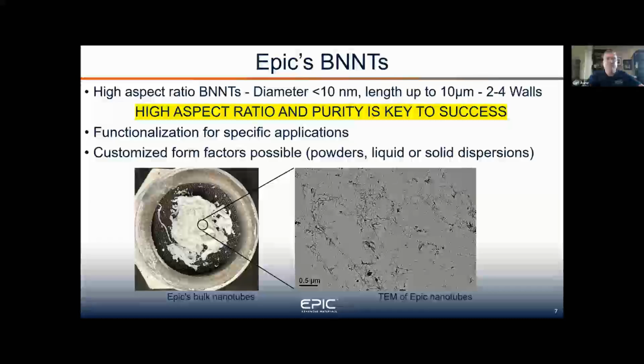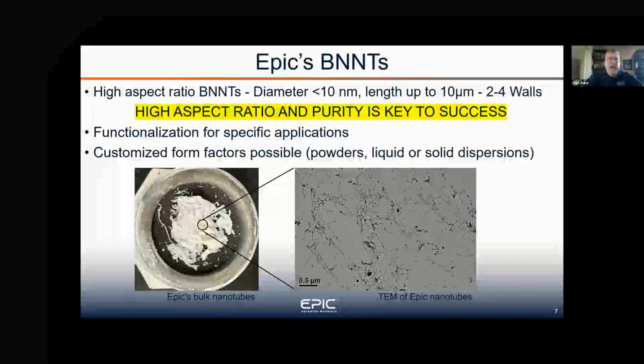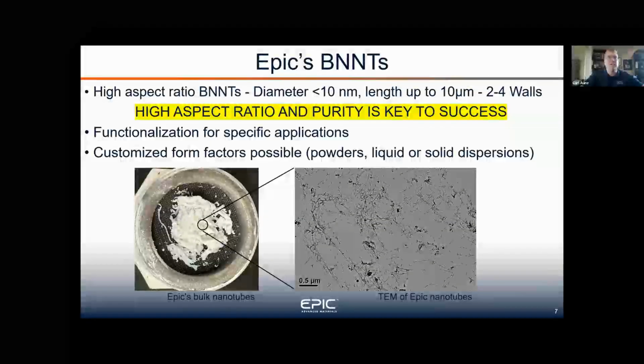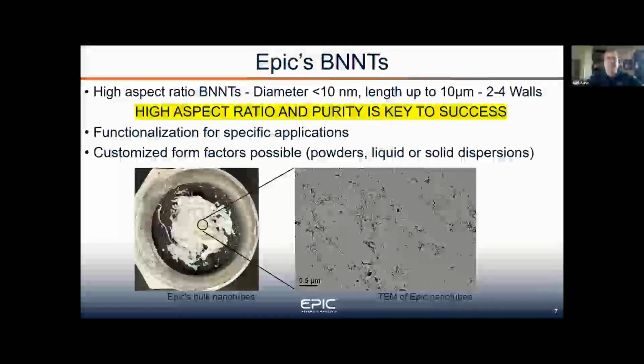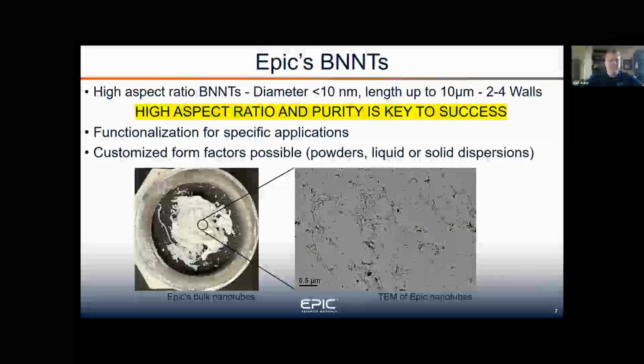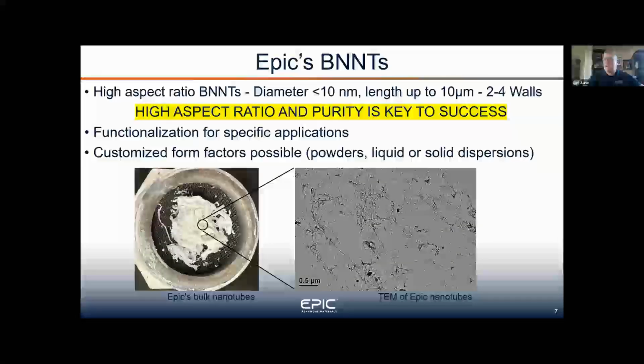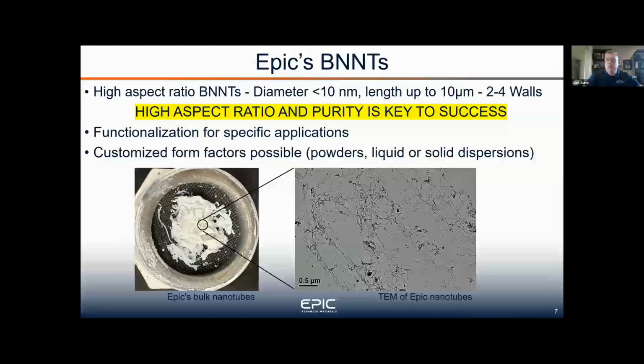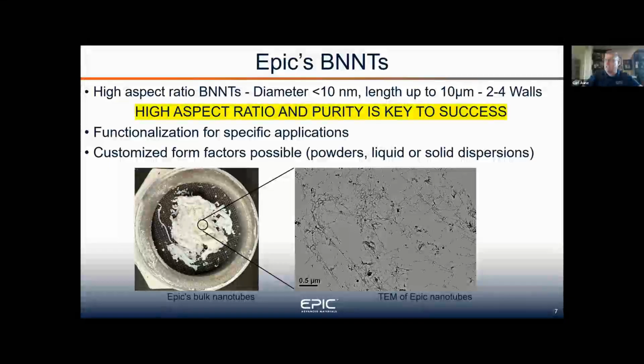Epic's BNNTs have a high aspect ratio. So again, that aspect ratio and purity is key to any kind of success in a resin system. The reason for that is that the higher the aspect ratio, the better the percolation of phonons across the matrix, and also how it acts as a nanofiber to hold the matrix together. We do functionalization for specific applications, specific resin systems, and I'll get into that a little bit more when we talk about blending. We offer customized forms, so in powders, liquids, and solid dispersions, depending on what the customer's end use is.